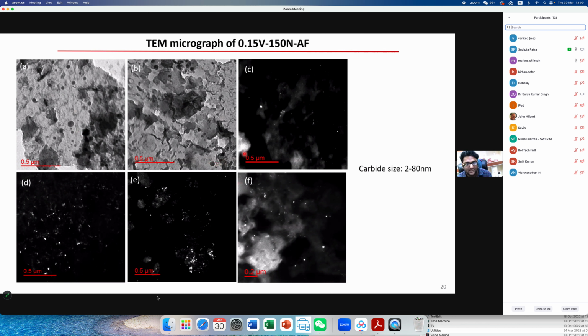So in the next presentation, we probably will be doing a good TEM study and quantify all the precipitates, because here we could only do 3-4 samples. We wanted to do more samples and then count the precipitates and their size, fraction, volume fraction, and correlate with the strength.